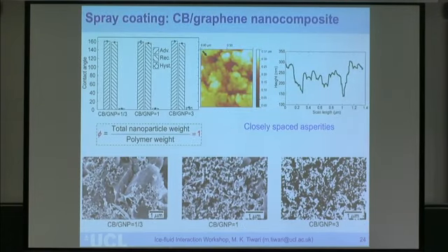Next step after that is if we can think of scaling to even larger areas, so we are not limited to the bath size. So what we did for that is we went back to the original image that I was showing you. We use hydrophobic polymers, we disperse them into solvents, we add some nanoparticles such as carbon black, graphene, carbon nanotubes, which are thermally conducting, to stay true to the idea that we want to make things thermally conducting, as I showed you with some results.